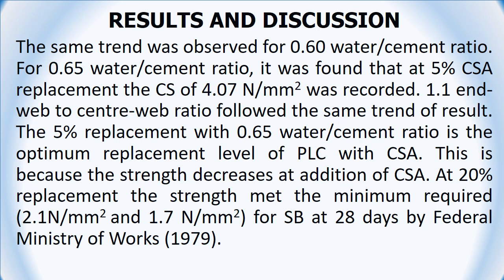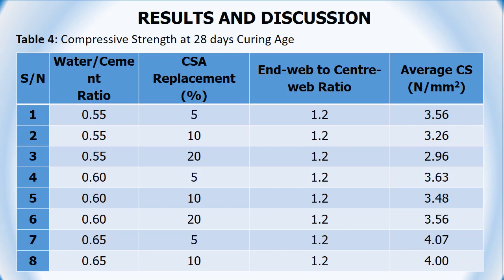This is because the strength decreases with addition of coconut shell ash. At 20% replacement, the strength reached the minimum required for sandcrete block at 28 days by the Federal Ministry of Works. The increase in the compressive strength can be attributed to cement hydration and pozzolanic reaction between Portland limestone cement and coconut shell ash. The reaction is prompted by the hydration of cement in addition of water.